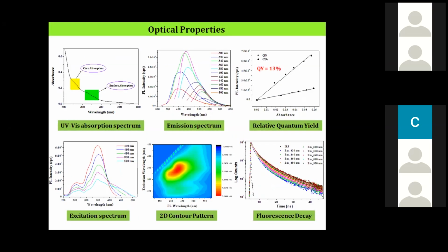And then we go for the photophysical studies on this material. When you look at the absorption spectrum, you have an upcoming, steeply rising absorption spectrum. One can see this is the surface absorption, and a little closer to the UV region is the core absorption of the nanoparticle.